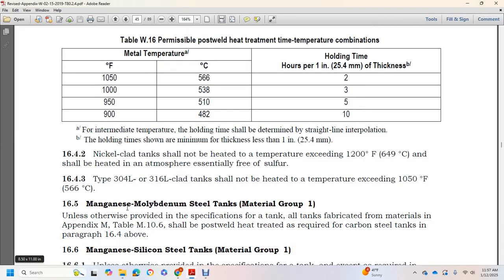Nickel clad tanks should not be heated to temperatures exceeding 1200 degrees Fahrenheit. They should be heated in an atmosphere free of sulfur. Type 304L or 316L clad tanks shall not be heated to temperatures exceeding 1050 degrees Fahrenheit.